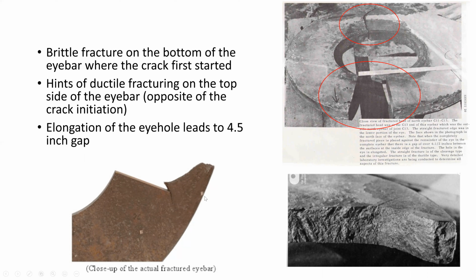And hence, elongation of the eye hole also occurred, resulting in a 4.5-inch gap when the eyebar was pieced back together for examination. It was found that the head of the eyebar was loaded with 3 times the amount of stress as other parts of the bridge, which could explain the amount of elongation in the eye hole and why the eyebar also had hints of ductile fracturing.